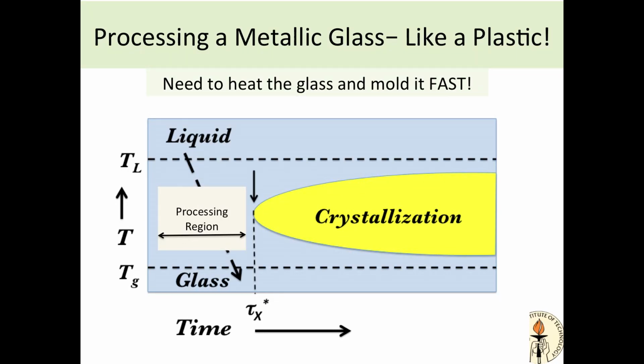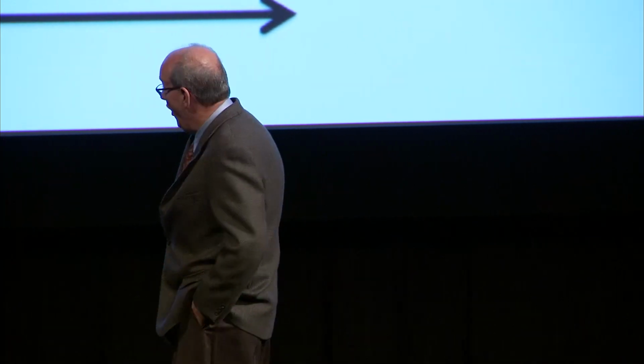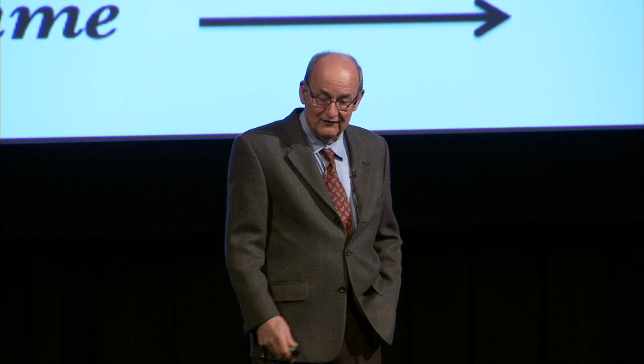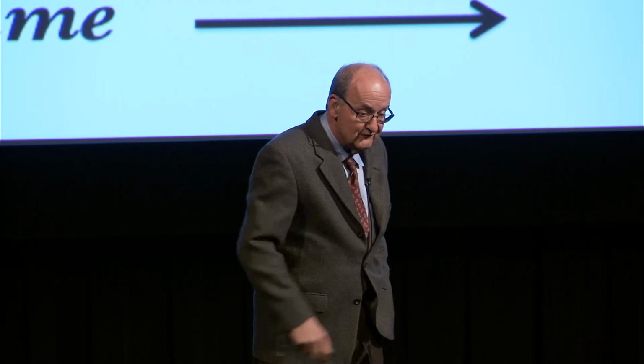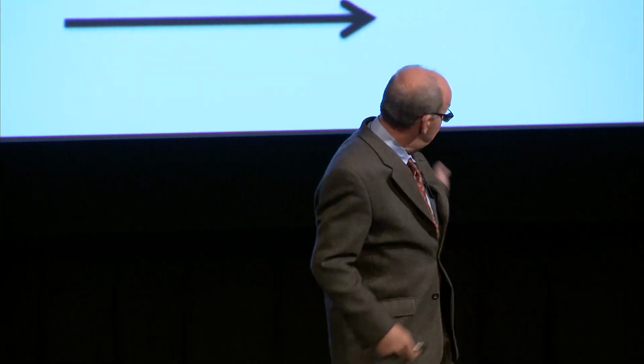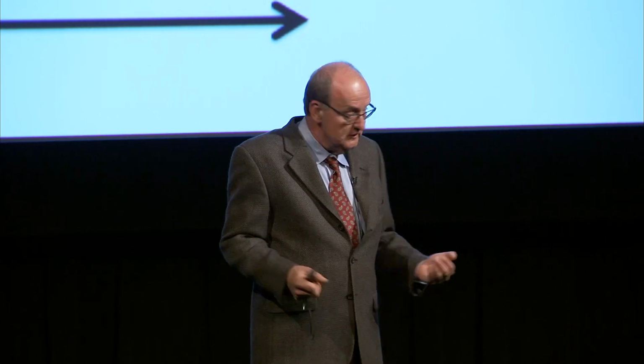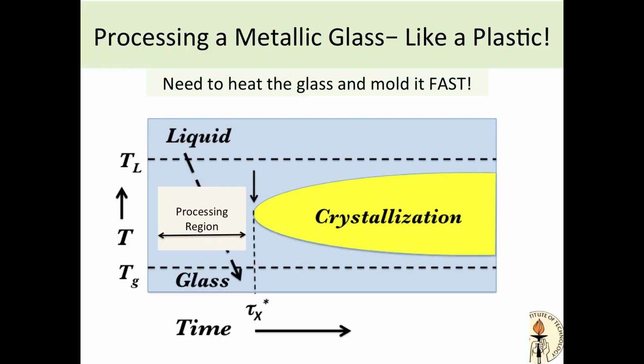So, well, back to Turnbull. We've got a certain amount of time. And we got to get up here where the viscosity is like plastic, and we've got to form it and injection mold it or do whatever we're going to do and get it cooled down and not get over here. Okay? Well, that's hard to do. It's not as stable as the crystallization curve of plastic is orders of magnitude longer. Silica glass that I blow mold, the crystallization curve is 100, 1,000 times farther away. These are still not fantastic glass formers. They're good glass formers. So you got to get up here, do your forming, and get down again before you run into that. You got to go fast.